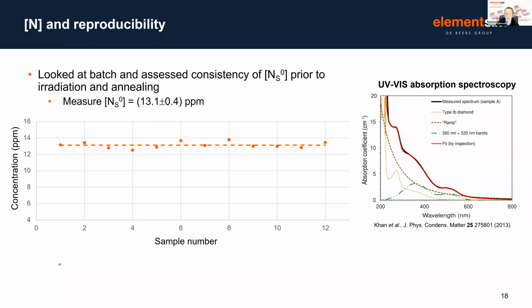So with that initial result at our disposal, we started looking at the reproducibility of this process and this particular recipe. So for this, we produced a batch of material and assessed the consistency of the critical nitrogen concentration prior to irradiation and annealing, which again is the process that we're going to use to transform this initially present substitutional nitrogen bath to NV centers. Now, what we found in this initial batch of samples is that we had good control of the nitrogen concentration between samples, an average at around 13 parts per million, so pretty close to the level of 10 ppm that we were originally envisaging, with a very small scatter between samples. So it looked very positive.